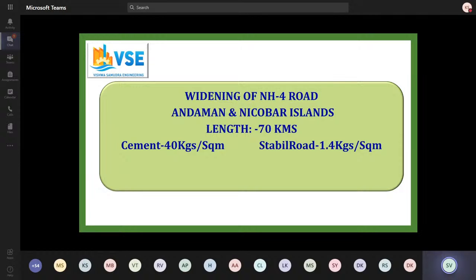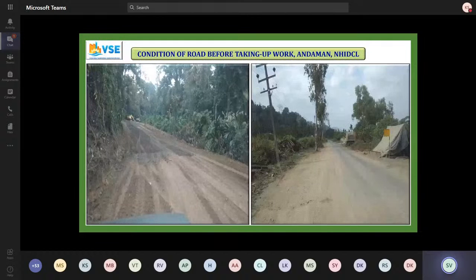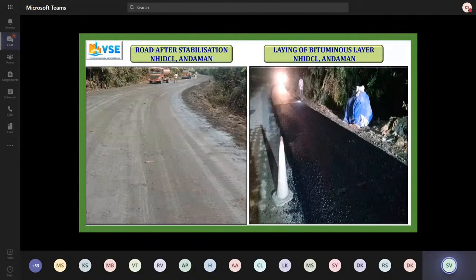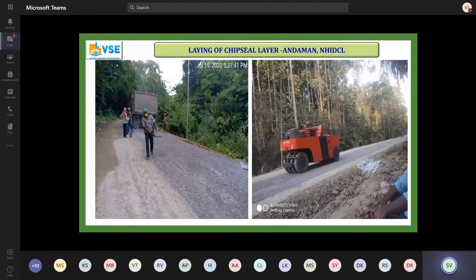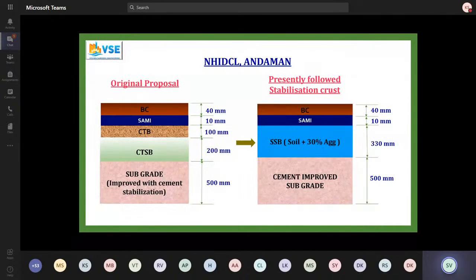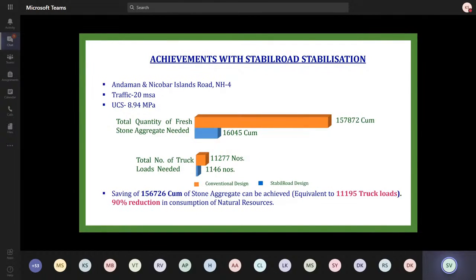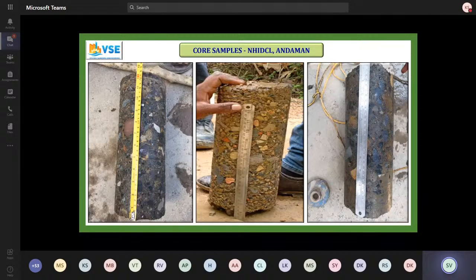So this is the road before taking up the work, and we're spreading cement and the additive, and this is after stabilization. They went for a chip seal and then went for a layer of BC on top. This is a chip seal being rolled on top of it. And this is the finished wearing course. Again, we've gone up to a depth of 330 mm or 33 centimeters, followed by SAMI and BC. Here, if you see, we've saved almost 90% in aggregates. The traffic was 20 MSA, and the UCS we achieved was around 8.9 MPa after 28 days. On the existing road, there were some aggregates, so that's why you see aggregates here. Otherwise, per se, we haven't added any aggregate. Whatever was there, existing soil, we just churned it.